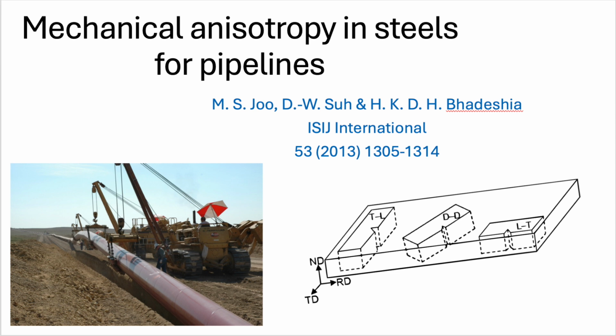Wow. Okay, so shape is king here. That shifts the focus for fixing it. How you control the shape. Well, the obvious first step is still reducing sulfur overall. You want clean steel. But even below 0.01%, anisotropy can persist. So cleaning isn't enough on its own.